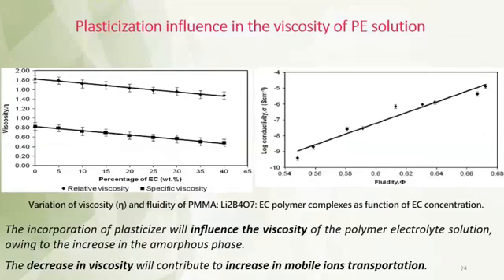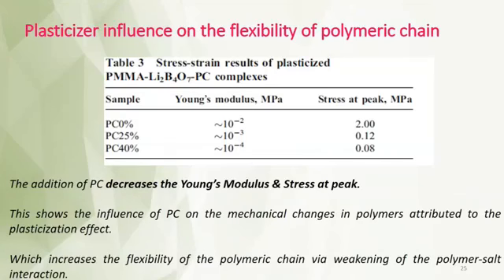Okay, next, plasticization also can influence the viscosity of the polymer electrolyte. The decrease in viscosity will contribute to an increase in mobile ion transportation. Okay, next, we also can see how plasticizers can influence the flexibility and the mechanical properties of the polymeric chain. So results here show that the Young's modulus value and also stress at peak values decrease with the incorporation of the plasticizers. So this shows that plasticizers can decrease the mechanical properties of the polymer electrolyte.